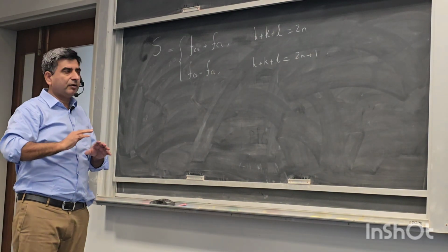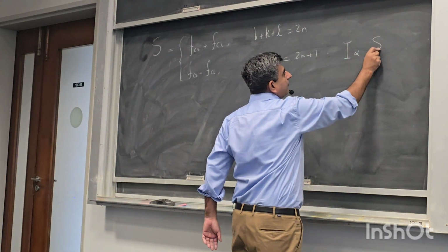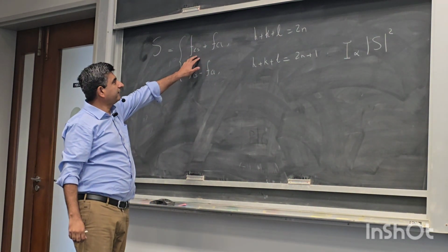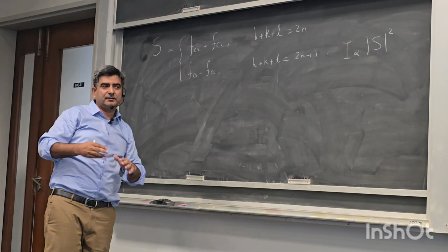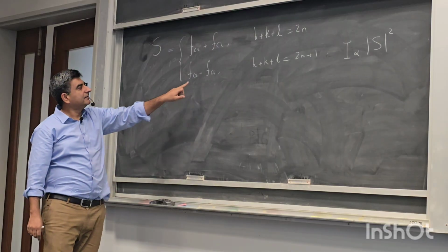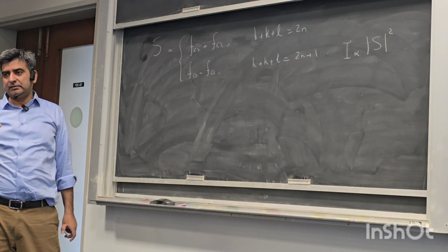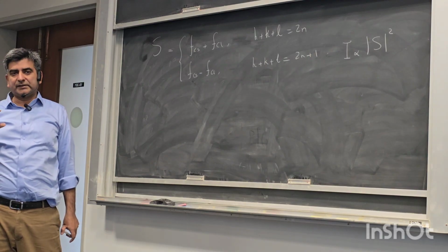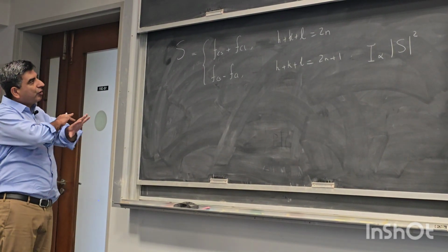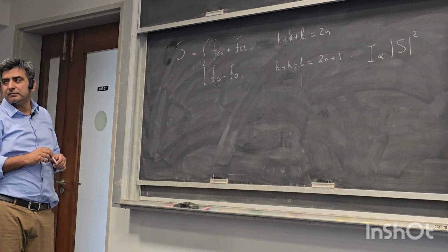So when you look at the diffraction intensities, now this is structure factor. The intensities will then be proportional to the square of S, mod S squared. So you'll get two kinds of intensities. One will have intensities (FCs plus FCl) squared, the other will have (FCs minus FCl) squared. By the way, these F's will also be dependent on the angle, as I'll show in a minute. Nevertheless, now all peaks in the diffraction pattern do not have the same intensity. Okay, any questions about this?